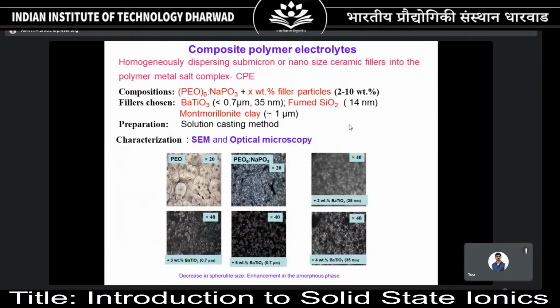So coming to the composite polymer electrolyte, I am showing some of these composite polymer electrolytes over here. Same polymer electrolyte which I have shown you earlier with the composition of 6 ether oxygens and 1 sodium ion. Now I'm adding different types of fillers. Here, polymer electrolyte with PEO and sodium metaphosphate act as a matrix, and different types of inorganic fillers, as I told here in the definition, homogeneously dispersing submicron size or nano size ceramic fillers into the matrix.